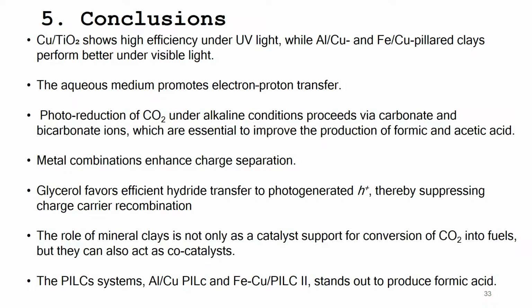Finally, the conclusions: copper over titanium dioxide works better under UV light, but the pillar clays that we have synthesized at the laboratory perform better under visible light. And the aqueous medium promotes the electron-proton transfer. How did we conclude that? Well, with the Bronsted and also the Lewis acidity. And then the photoreduction of CO2 under alkaline conditions proceeds via carbonate and bicarbonate ions. This was concluded by the pH study.